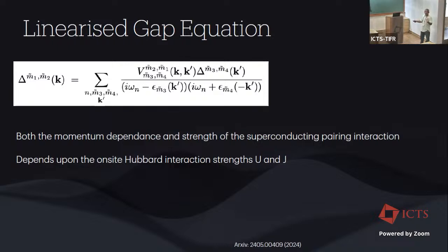and you, let's say, use Gorkov equations to derive your BCS gap. Then the most generic BCS gap that you get, if you assume that the single particle Hamiltonian has a spin orbit coupling but does not have spin flip terms in it that you can have in Rashba, is a gap which looks like this. It doesn't look exactly like the BCS gap we have seen out here. You can derive the BCS gap by just choosing inversion symmetry, which means that this energy is equal to this energy. You'll get your standard BCS gap, but it is a slight generalization that comes in.